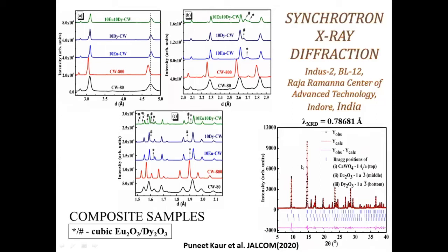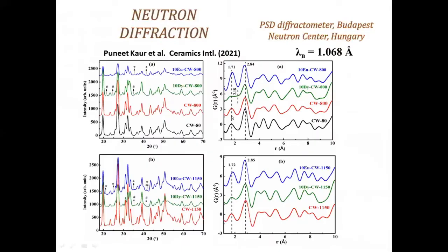These are the Rietveld refinements of calcium tungstate doped with europium oxide and dysprosium oxide. The XRD patterns confirm that the europium ions and the dysprosium ions do not replace the calcium ions in the structure, but europium oxide and dysprosium oxide phases exist separately. We did neutron diffraction studies, because if you want to study the position of the oxygen ions in the structure, then we need neutron beams, because X-rays do not see light elements like oxygen. And the neutron diffraction studies also confirm that the two phases of calcium tungstate and the rare earth oxide occur separately.